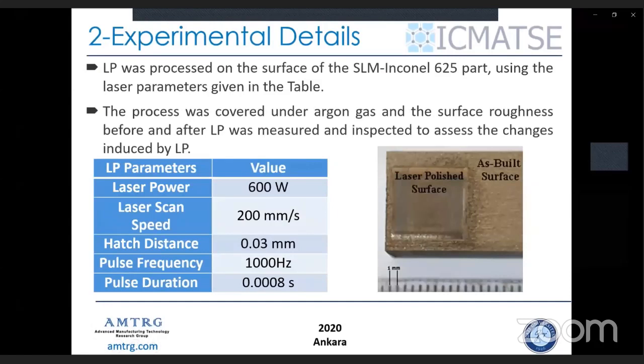Laser polishing was processed on the surface of the SLM Inconel 625 part using the laser parameters given in the table. The laser power was selected as 600 watts. Laser scan speed was 200 millimeters per second. Hatch distance, which can be defined as the distance between two laser tracks, was 0.03 millimeters. Pulse frequency was 1000 Hz and pulse duration was 0.0008 seconds. The process was covered under argon gas because oxidation was a problem in this process, and the surface roughness before and after laser polishing was measured and inspected in order to assess the changes induced by laser polishing.